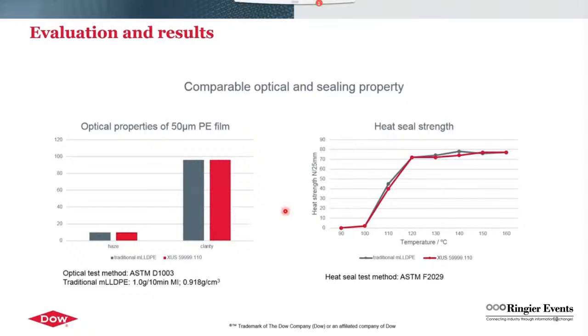Here, the optical and heat seal properties of the film were also measured. The graph on the left-hand side compares the haze and clarity of the polyethylene films using both formulations with the traditional metallocene LLDPE sealant and the COF stable resin XUS 59900.110. The results show that the haze and clarity of both polyethylene films are very similar.